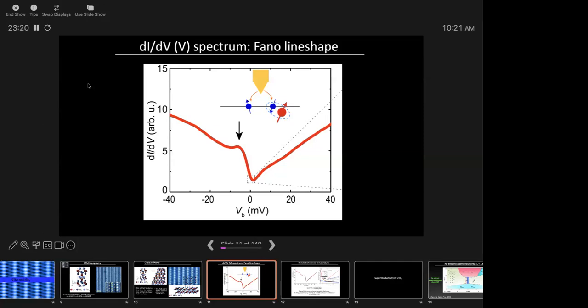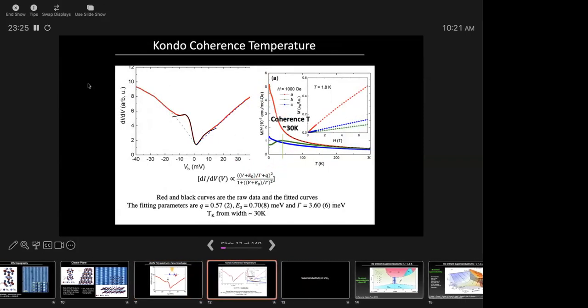Okay, so this is the Fano line shape. The nice thing about knowing what this is, you can fit it, and this black curve here is the fit, and from that you can get the width of the resonance and the position of the resonance. From the width, you can get the Kondo coherence temperature. The Kondo coherence temperature from the width is about 30 Kelvin, which is right here, exactly where I should have shown you earlier, where the resistivity starts going down. Okay, any questions about this before I proceed?